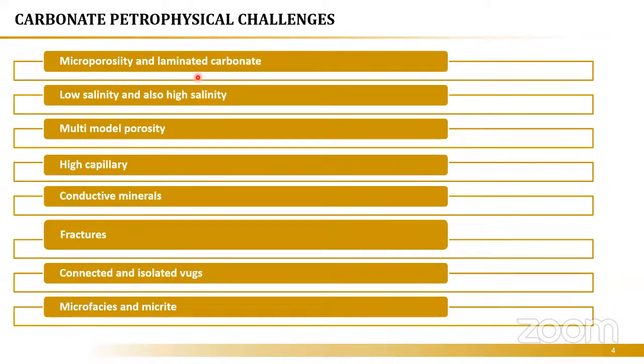Moving to this slide, it indicates the challenges that you are going to face when doing a carbonate petrophysical evaluation. You need to understand the carbonate in your field. Does this carbonate have microporosity? Is it laminated? Does it have low salinity or high salinity? Because I saw before a carbonate reservoir with salinity of 200 K, so the resistivity was 1 ohm and it was producing oil with a water cut of 0%. So you need to know the salinity of your reservoir because it will affect your resistivity.